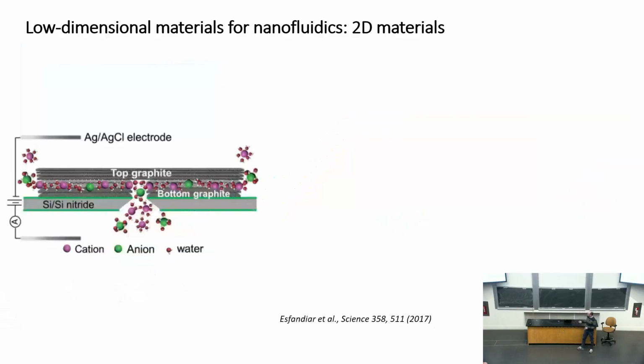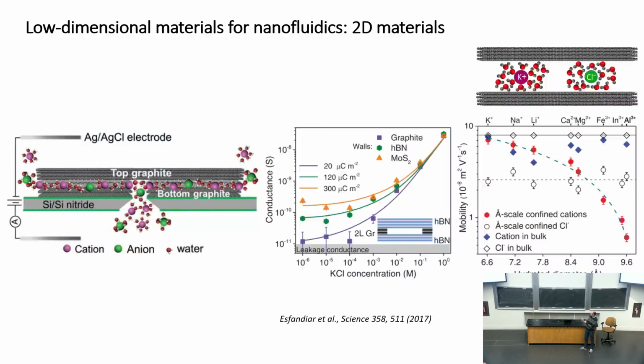It's actually possible to make this as thin as two atomic layers or one. Here are examples of measurements where only two sheets have been taken out. You can see conductance curves as a function of concentration for different ions. These platforms allow you to look at steric effects versus charging effects, like which ions can enter the pore easily and which don't.